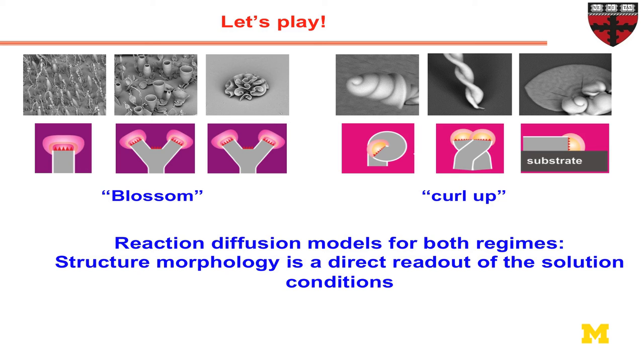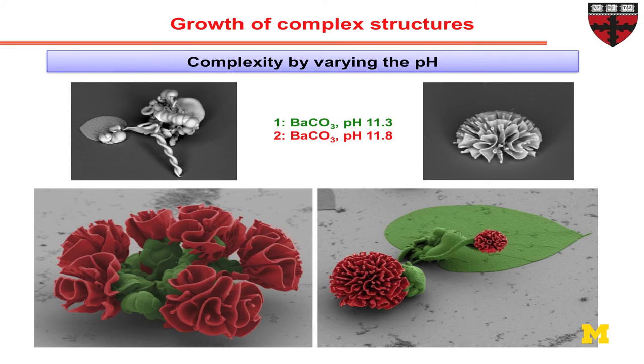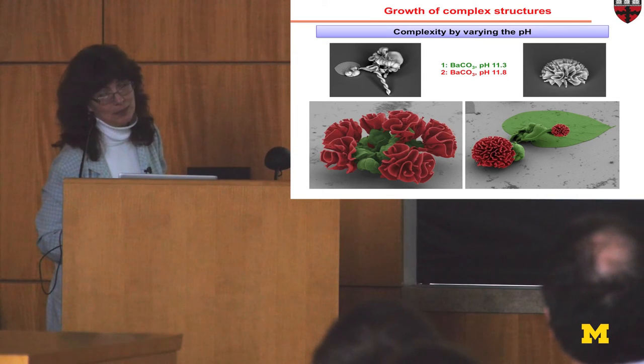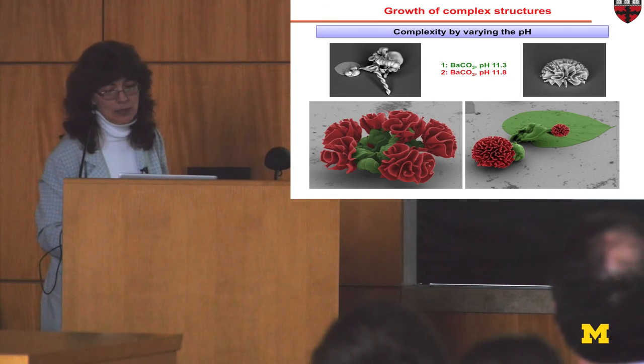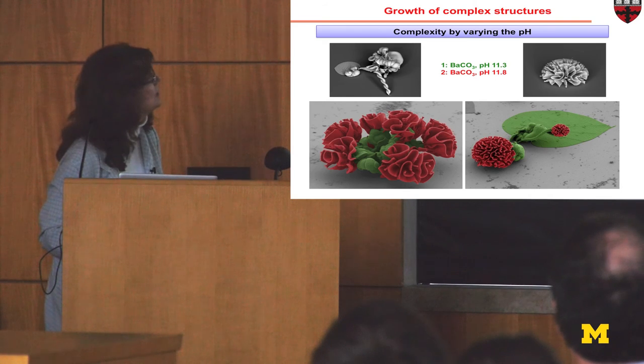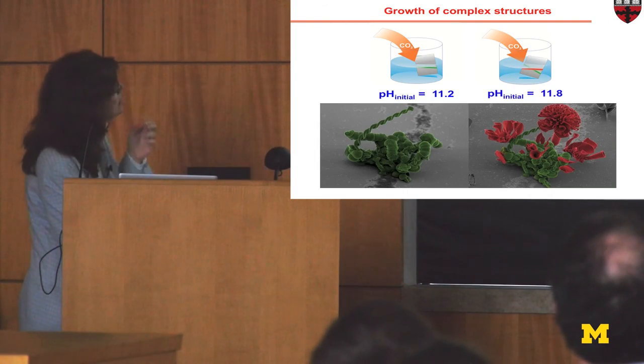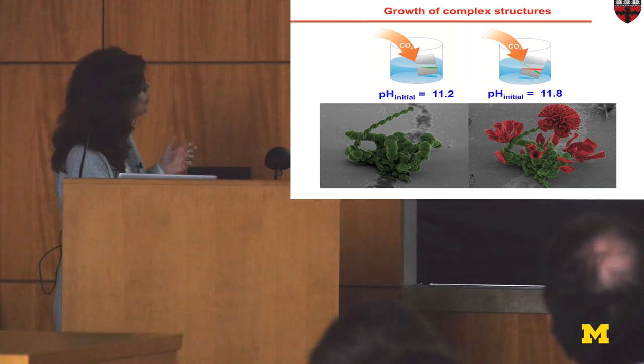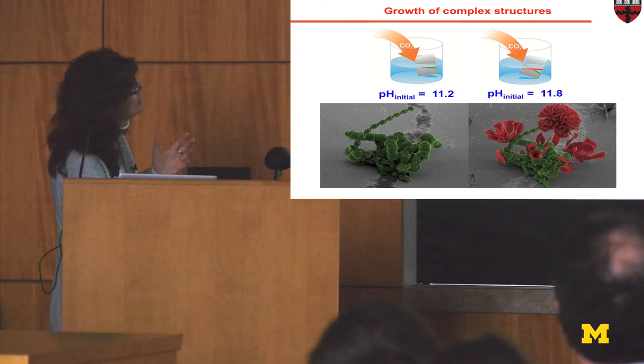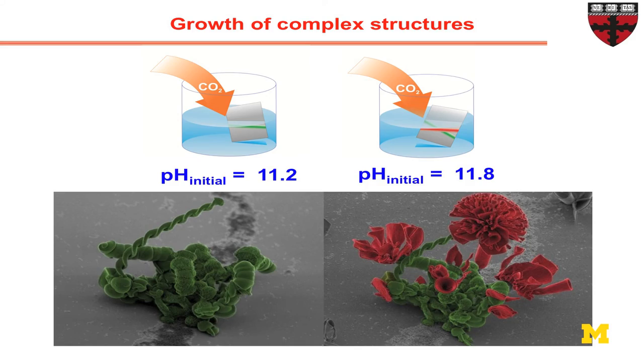Each of them has a very special part in the phase diagram, and here are structures that we can grow. So that's about 50 micron in size, and yes, it's of course a colored electron microscopy picture, but it doesn't have to be artificially colored. I'll show you in a second that in fact, this is first. What grows first is the green part. You see nothing on it. And then the red part will grow. And there's a way you change the conditions in this particular case. Just by changing a little bit the pH in the system, it starts to grow flowers, and only at the tips of these, nowhere else, it's allowed to form.